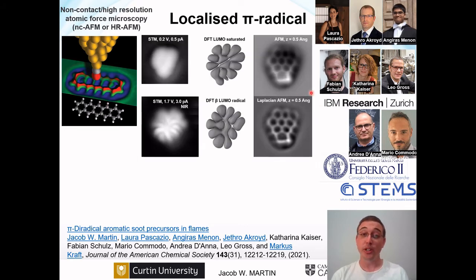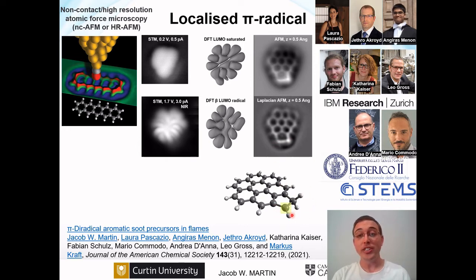So this is the first molecule that I want to show you. This molecule here is an aromatic molecule, and it has two pentagons on the outside. Now, I just want to zoom in on what that looks like. And you can see that around this site, there's actually two hydrogens here and one hydrogen here. And you can see what that looks like here. This means that there's an odd number of electrons in the pi network, which means that this is a radical.